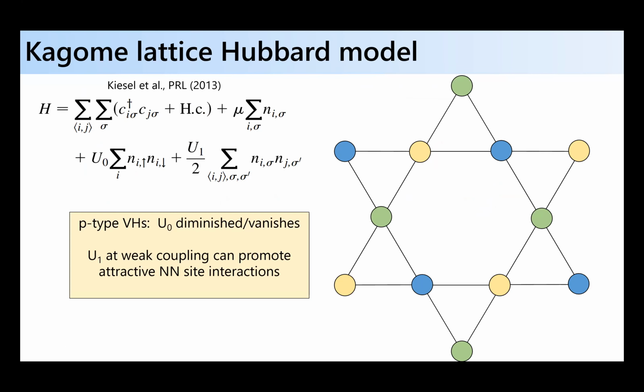All right. Okay, so the second bit is that there's been a lot of beautiful work done looking at the kagome lattice Hubbard model, where if you can tune it towards this P-type Van Hove singularity, there are, in the weak coupling limit, some odd things predicted to occur, meaning that the on-site Coulomb interaction is predicted to be severely diminished or to vanish. Instead, the nearest neighbor Coulomb interaction can dominate and can promote attractive nearest neighbor interactions and unusual forms of superconductivity. So, electron-electron mediated pairing. All right.